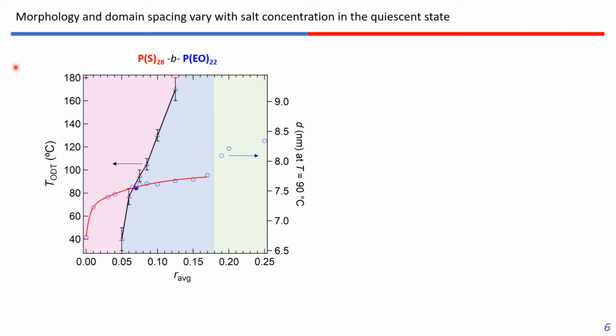In order to make sense of the results of this experiment, we first want to understand the morphology of the block copolymer electrolyte as a function of salt concentration in the quiescent state. Here I'm plotting the phase behavior as a function of the average salt concentration in the electrolyte. At low salt concentrations and high temperatures, we observe a disordered morphology where the polystyrene and the polyethylene blocks are homogeneously mixed. But if we increase the salt concentration or decrease the temperature, we get this lamellar morphology in the blue region. And if we further increase the salt concentration, we get the gyroid phase in the green region. On the right axis, I'm plotting the domain spacing, which is also measured from small angle X-ray scattering, as a function of salt concentration.